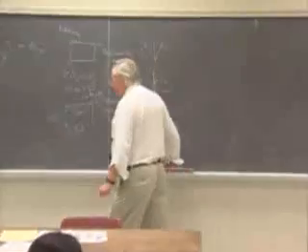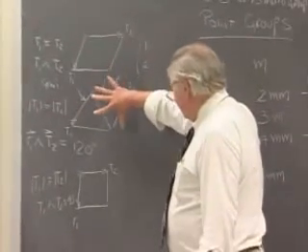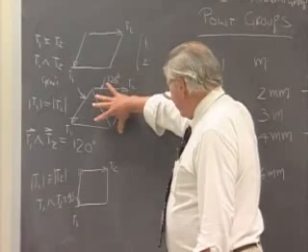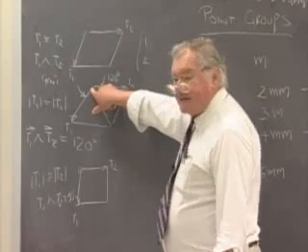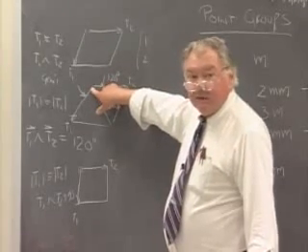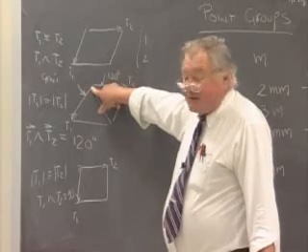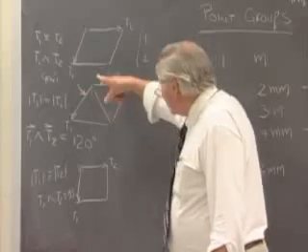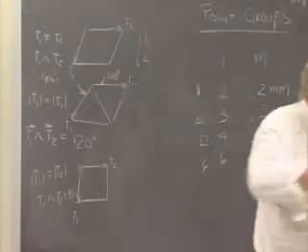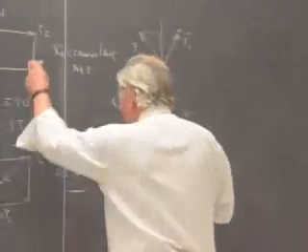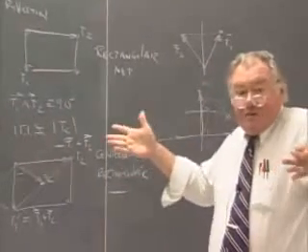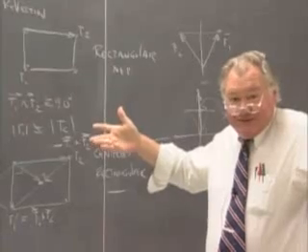So there's a curious sort of duality here. Here in the case of a hexagonal net, this is just a lattice of a very specialized shape. Does that have a six-fold axis in it? No, not unless I decide to put one in. I could put in a three-fold axis alternatively. So here I have one lattice that can accept two different kinds of symmetry. Here I've got the reverse situation. I have two distinct kinds of lattices, both of which are happy and content with the same symmetry element.